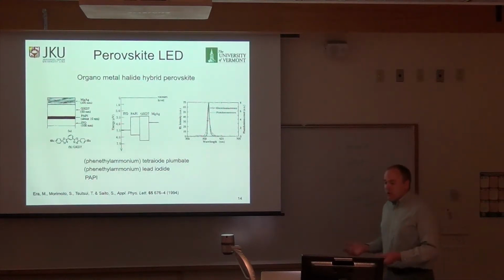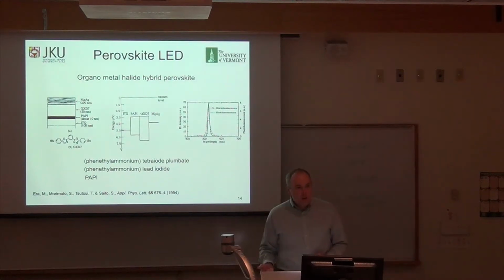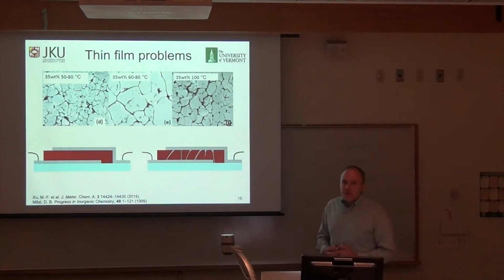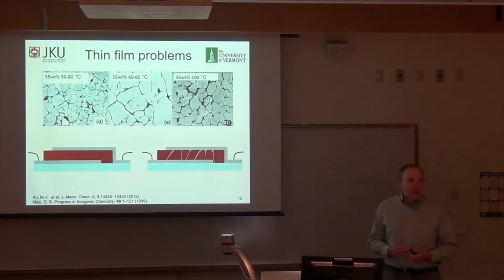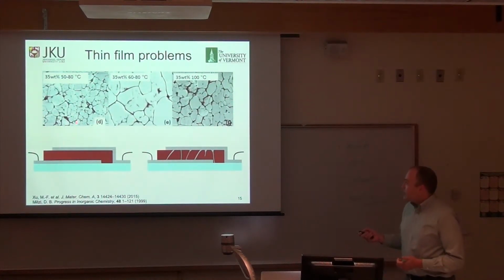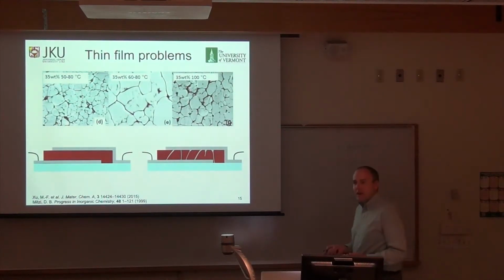Now, currently, we're seeing a perovskite revolution going on. It started a couple of years ago. Why didn't the revolution start in 1994 when these guys demonstrated it can be used as a functional electronic material? The answer is that it is incredibly hard to make thin films out of this salt, which likes to crystallize. If you put this stuff down, it forms crystals with holes in it. And if you're trying to make a thin film device with two electrical contacts, and there are cracks, you're always going to have parallel pinhole shorts.